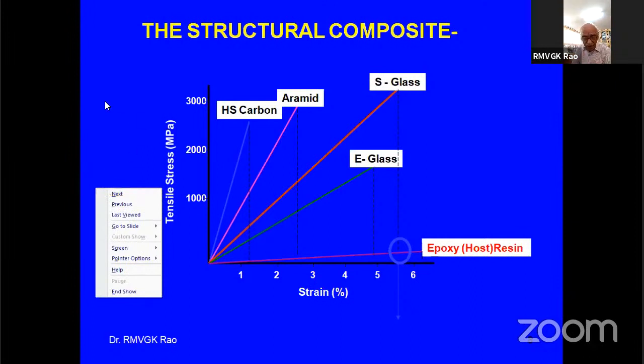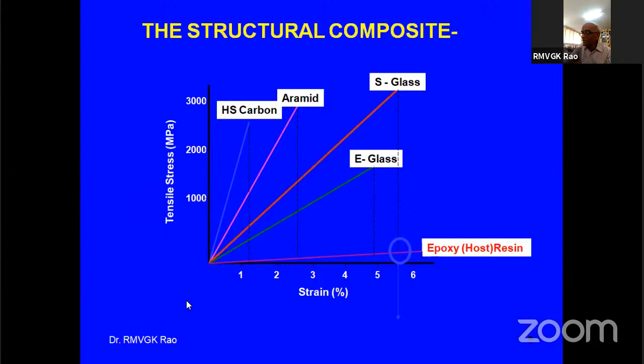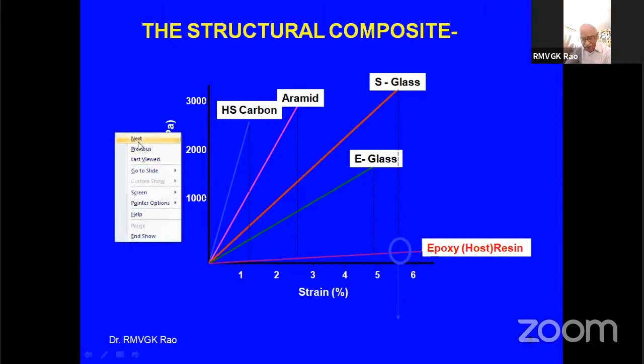That is the radar dome, which will be an electromagnetically transparent window. That means a carbon fiber acts like a metal layer reflects it. So carbon fiber is a taboo. Only glass fiber of a special grade, a quartz fiber or an L-glass, radome glass, you use it, where it gives a very good epsilon tan delta values. We have worked on this in radome engineering. Some of my colleagues in electromagnetics helped us. So the important message is that glass fiber, though it is looked down upon in some sense, there are some areas where you have only glass fiber, that is the radomes. You can't use any other fiber.